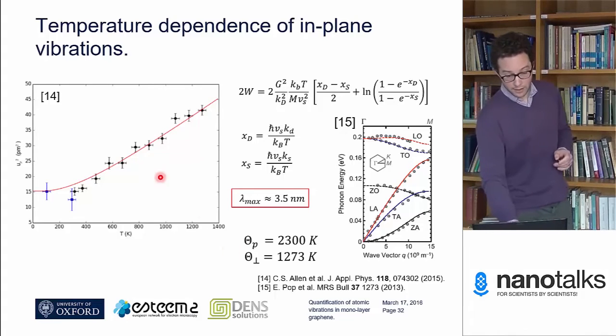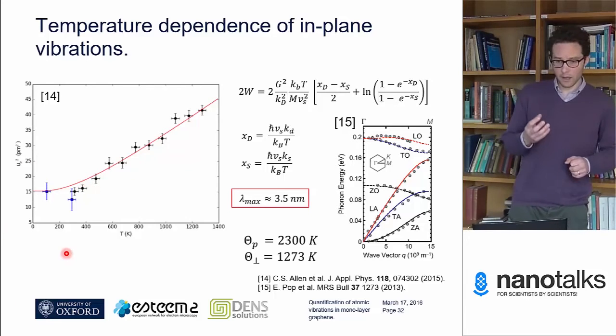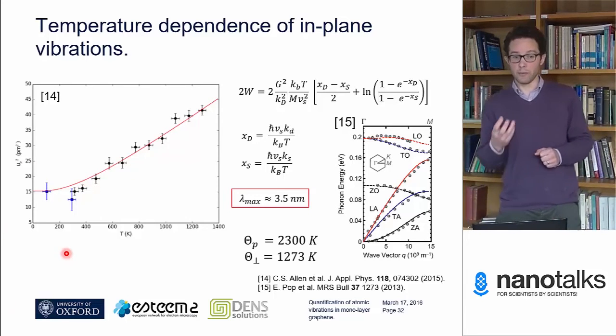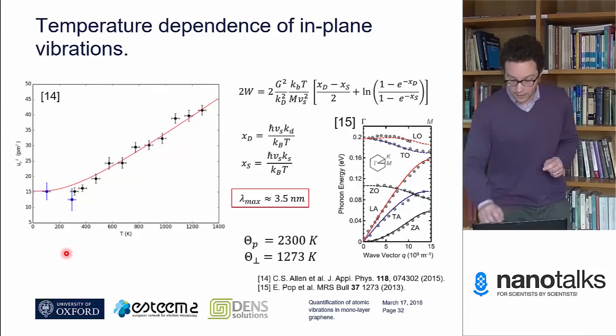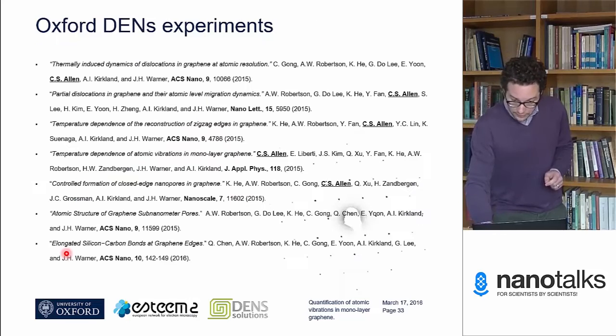From our experimental data, it would suggest that even up to temperatures of a few hundred Kelvin, the mean square atomic displacement, so the atomic vibrations, are dominated by this quantum mechanical zero-point energy rather than phonon contributions. I think that's quite interesting. So that's the end of my talk.